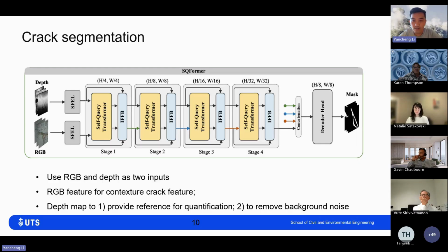Second, we remove the background noise, because for many pipe cracks you have water stains, many other things, and sometimes some plants. Based on the depth feature, you can observe the feature change. For example, a sudden depth increase indicates there may be a crack. So you can remove all the other image noise or disturbance, and make the measurements more accurate.